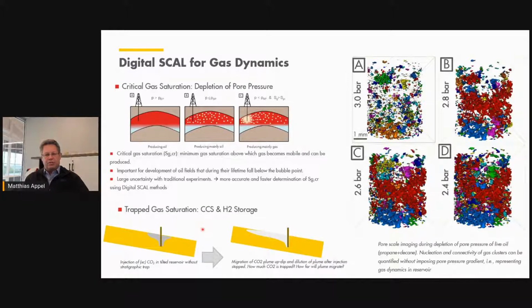Another application is what's called the trapped gas saturation, and it has a huge impact on carbon capture storage or hydrogen storage. Just imagine the situation. You have a tilted reservoir, you have an injector well, you inject a certain amount of CO2 in that reservoir. The CO2 will slowly migrate upwards in that tilted reservoir. Now, while it's migrating upwards, it's diluting itself because a certain amount of gas remains trapped in the pore structure.